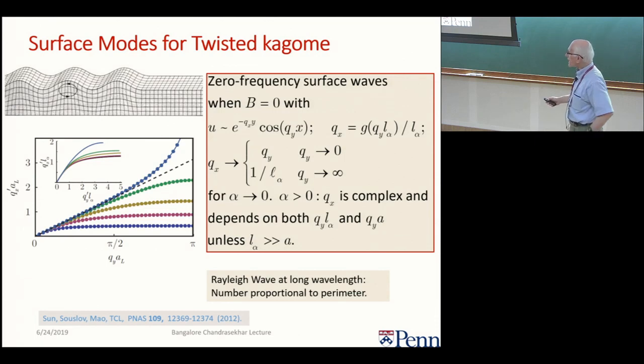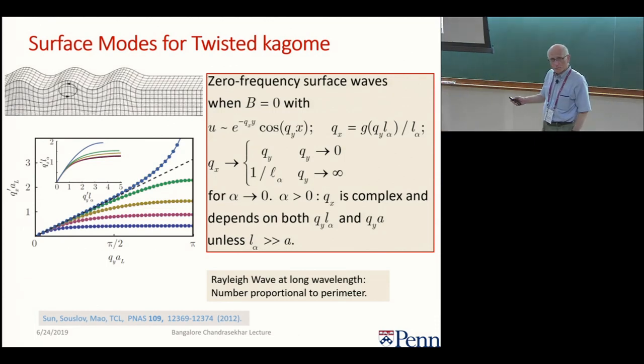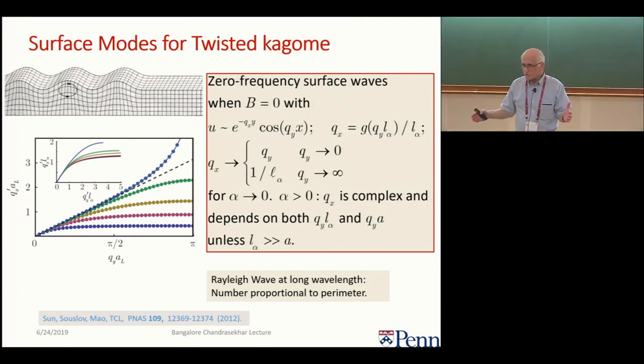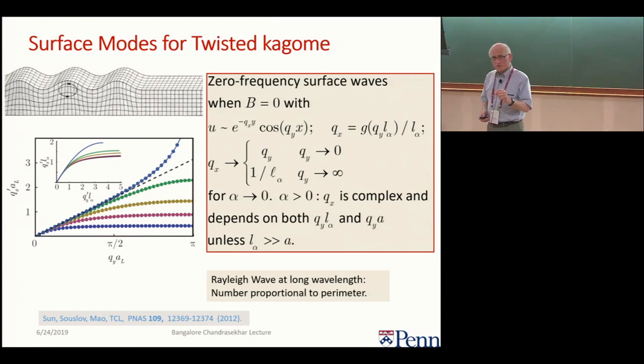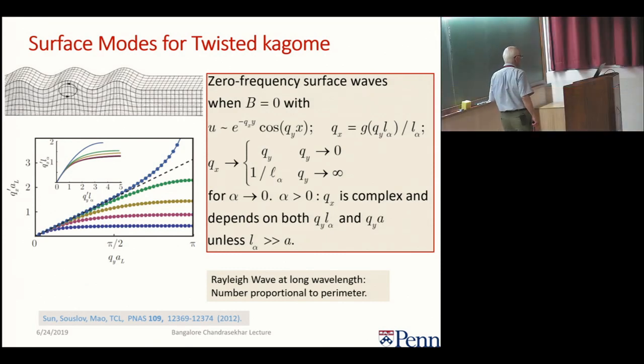And that is because at the long wavelength, in other words, small q, this lattice is described by continuum theory, which you can go look up in Landau and Lifshitz. And you can look at what the velocity of the Rayleigh wave on the surface is in that long wavelength limit when your bulk modulus is 0. And the calculation says that the energy is 0 and that the inverse penetration depth is exactly equal to the wave number along here for an isotropic system, which is the case for the Kagome lattice, the twisted Kagome lattice.